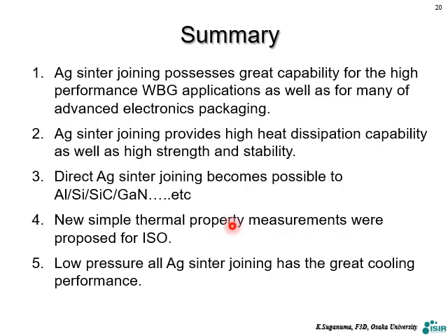Okay, here comes the summary. I showed the properties of the silver sinter materials we have developed, and it provides great heat dissipation capability, not only strength and reliability. And the good news is silver sinter material can be bonded onto many substrates or devices directly without any metallization. And the simple thermal property measurement method made a great demonstration of the capability of cooling the silicon carbide device.